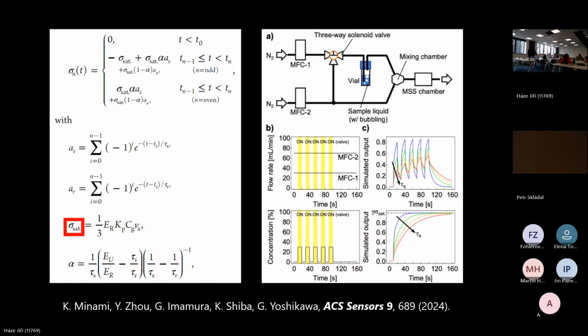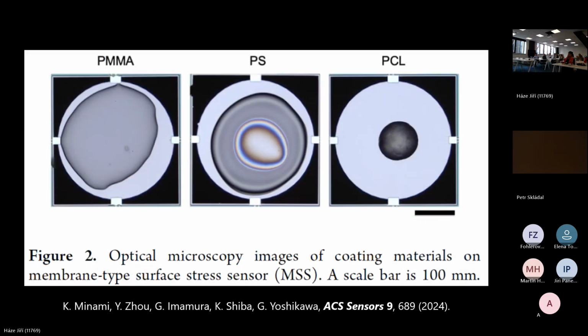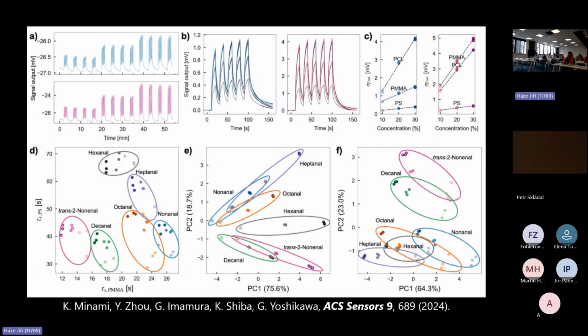So these are the analytical models and extracted parameters from the analytical model. And this signal amplitude corresponds to the sensing signal's intensity. And this time constant corresponds to the shape of the sensing signal. So with these polymers coated on the sensors, we measured these gases and found that the signal intensity clearly correlates with concentration as expected. And also, we confirmed that the time constant can differentiate these gases very clearly.